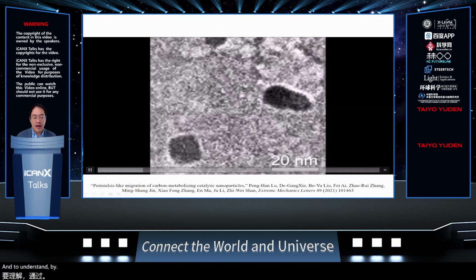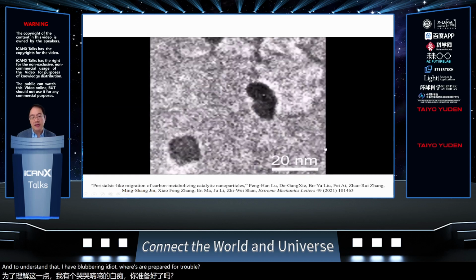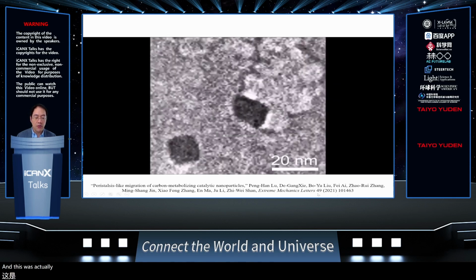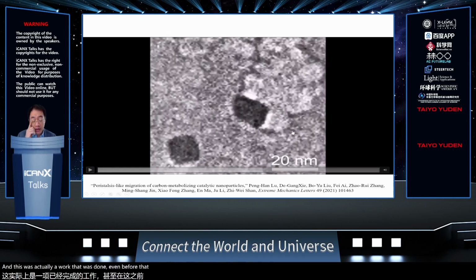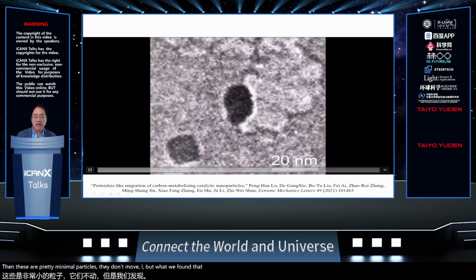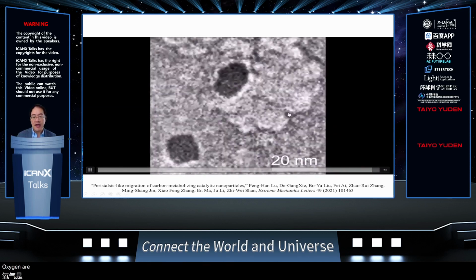And to understand that, I collaborated with Professor Zhi Weishan at Xi'an Jiaotong University. This was actually work that was done even before that 2018 work. It was only recently published, where we put some palladium nanoparticles on a silicon nitride support. We then give it a temperature of 300 Celsius and also pass some oxygen gas in the transmission electron microscope. The scale bar here is 20 nanometers. If we don't heat it or if we don't give it oxygen, then these palladium nanoparticles don't move. But what we found was that when there is both temperature and oxygen, they actually start to move.